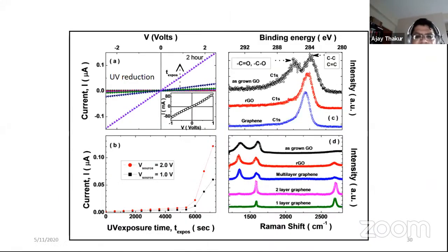Okay. So the next thing in line was to see what the various properties of this graphene oxide that we made are. One of the preliminary tests was to make a 4-probe contact on this graphene oxide. Because graphene oxide is highly insulating in character, unlike graphene, we started reducing graphene oxide so that gradually we could see current emerging at voltages as small as 1 volt, and then at 2 volts one could see significant currents after